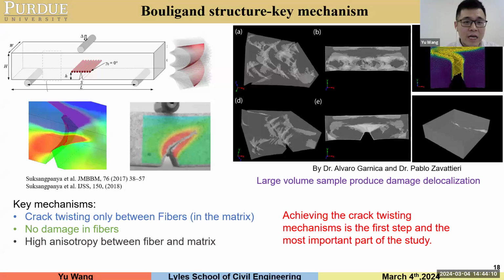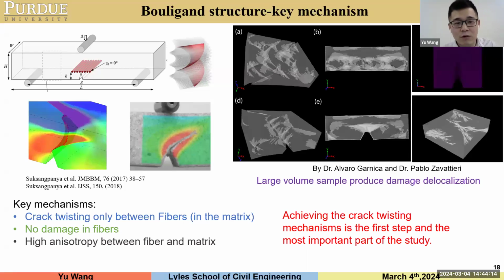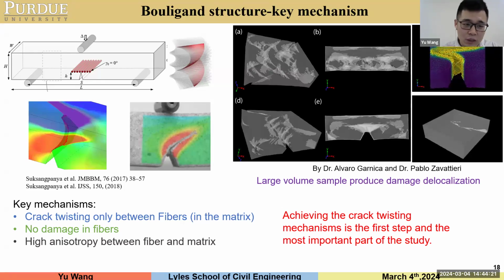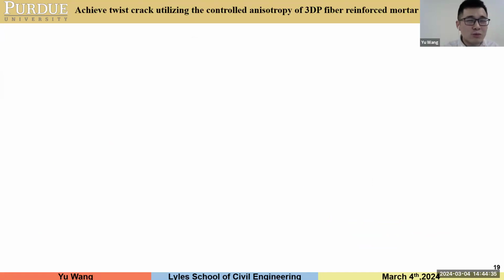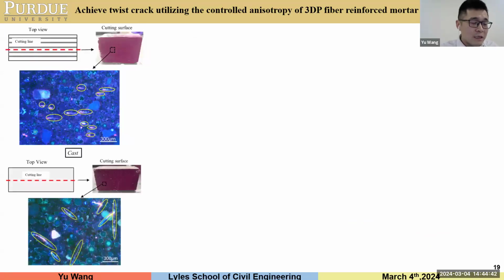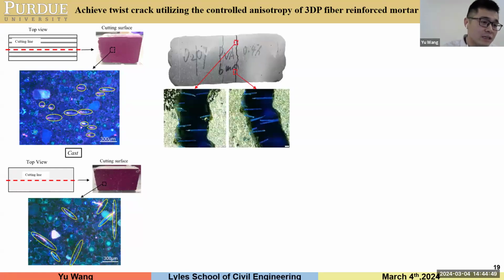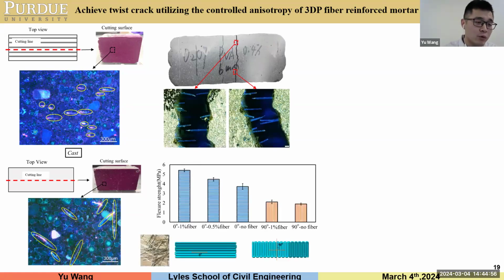When our sample has a large volume, which means we have a high volume of interface, this structure will promote damage delocalization and more micro crack development to improve the toughness of the sample. So we started to figure out how to replicate this key mechanism, since it's really important. First, we need a highly anisotropic material. We found that when we 3D print concrete with fibers, the fibers preferably align during the printing process, which means if we print in different filament orientations, we will get highly anisotropic properties.